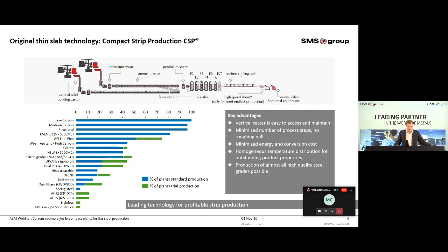The standard production mode is batch, so coil-to-coil production. That means that the slabs are cut after the casting machine to coil weight. With the help of a high-speed shear, a CSP plant can produce in semi-endless mode. A very long slab is produced, rolled, and cut into multiple coils right before the coiler. This mode increases the production stability when rolling thin strips.